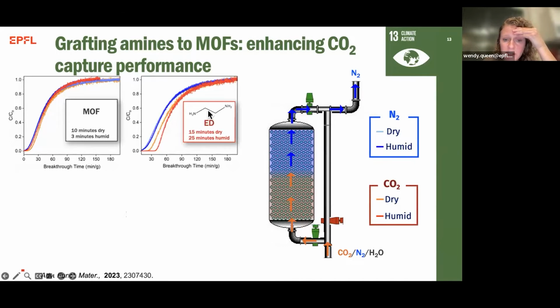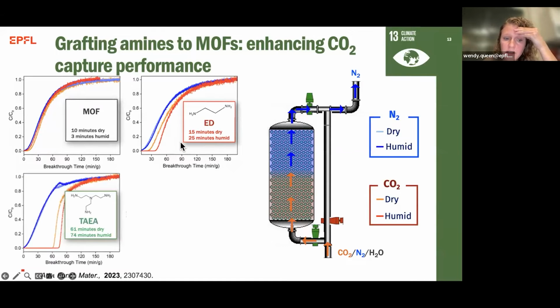As we add our amines, this is the first amine, ethylene diamine. You can see under dry conditions, we've already made an improvement. The breakthrough goes to 15 minutes. And then under humid conditions, it improves significantly. Again, as we increase the number of primary amines, we begin to see really large separations between nitrogen and CO2 under dry and humid conditions.